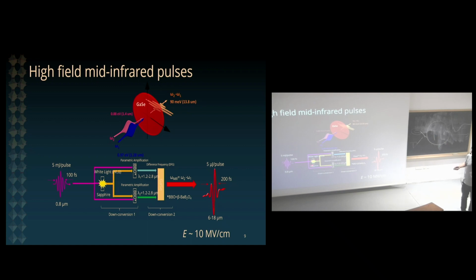So the first process is a white light generation that is followed by optical parametric amplification and then difference frequency generation. And after these processes have occurred, we can obtain mid-infrared pulses with a tunable central frequency between 6 and 18 microns, so that's the wavelengths, which last something of the order of 200 femtoseconds, and carrying an energy of the order of 5 microjoule per pulse. So you see, we started with 5 millijoule, and we end up with 5 microjoule, so we paid a big price to go down in frequency, in energy, but the electric field that we find in these pulses is still of the order of 10 megavolt per centimeter. So at 10% of our atomic electric field, we can think of exciting some significant atomic motions.